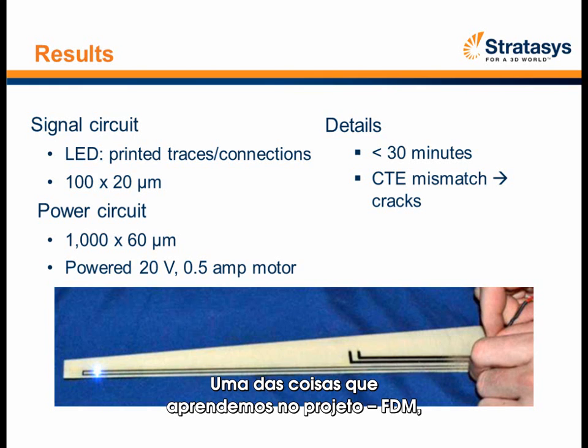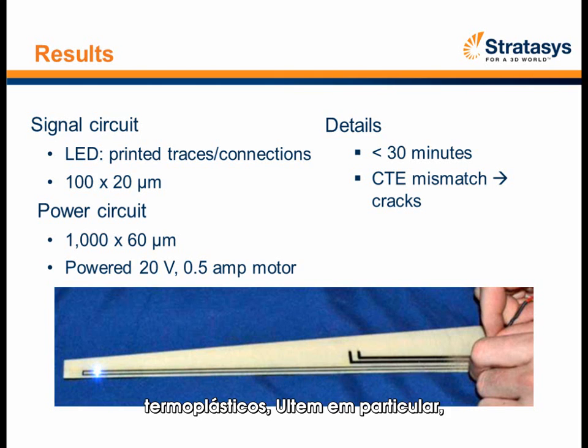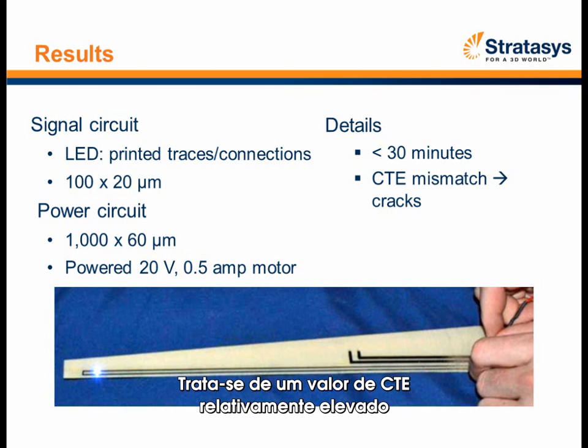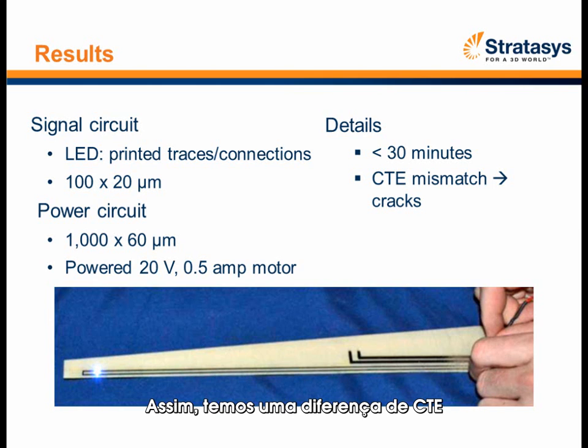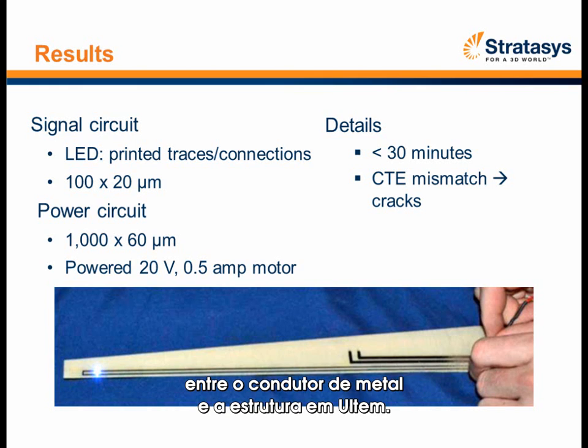One of the things we did learn on the project, FDM thermoplastics, Ultem in particular, has a CTE value of 4 times 10 to the minus fifth. That's a fairly high CTE value in relation to metals, which is a 10 to the minus 6 number. So an order of magnitude different. So we do have a CTE mismatch between the metal conductor and the Ultem structure.